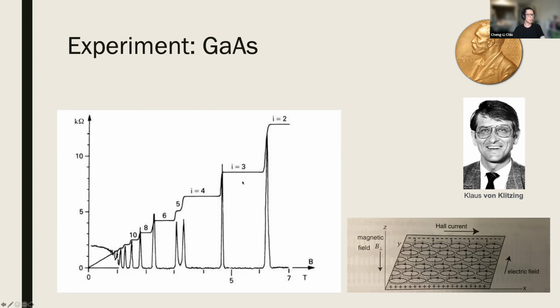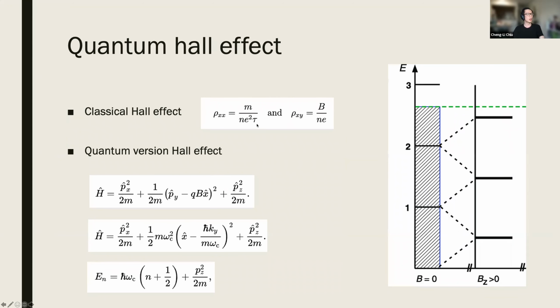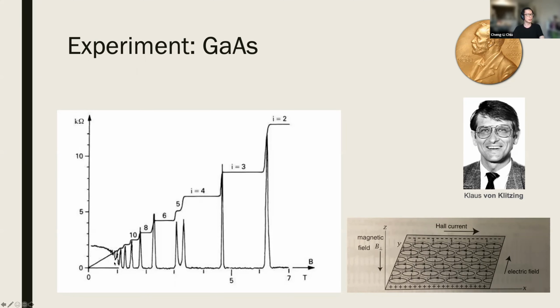You will see resistance change in R-xx and R-xy. When you are fully filled, you will see a change, a discrete jump, and this jump can be related to h over e squared, this kind of quantized resistance. And this is a very interesting behavior, because in the traditional Hall effect, you are expecting the resistance to be proportional to the magnetic field. However, in this diagram, you can see it has a lot of discrete jumps.